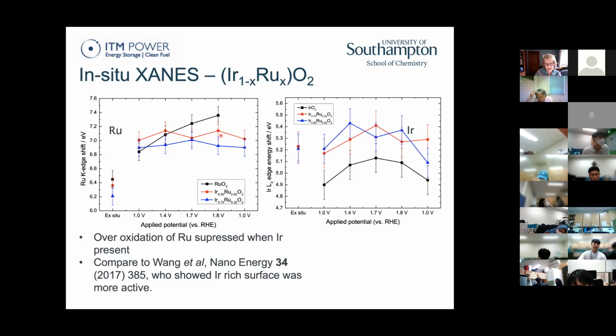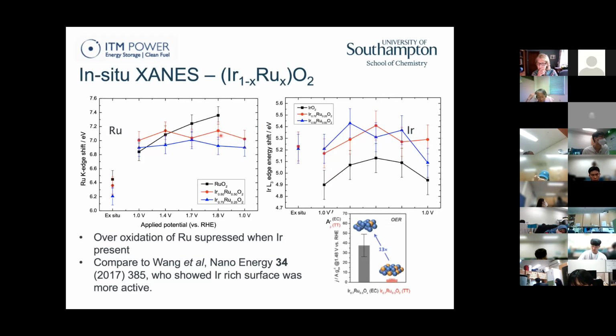with potential. And so what we think happens is that when you have the mixed material, you get an iridium enriched surface. And this is also something that was found in some thin film studies by Wang's group, right? So if you have iridium sitting on the surface of the particle, on a ruthenium-rich surface, you get enhanced activity. And so we think the enhancement here comes from the fact that the ruthenium in the underlying layers is increasing the activity of the iridium on the surface.